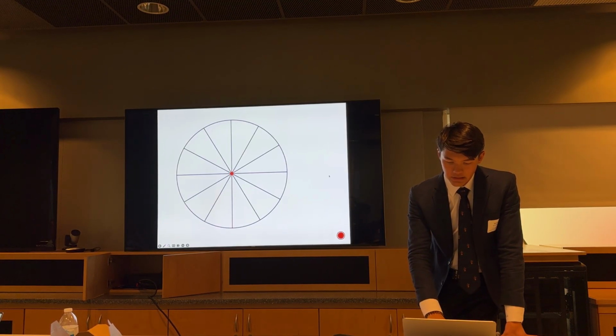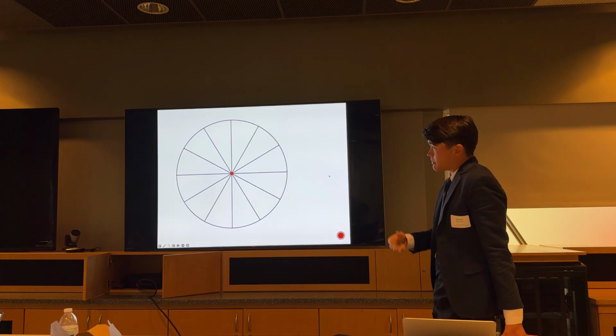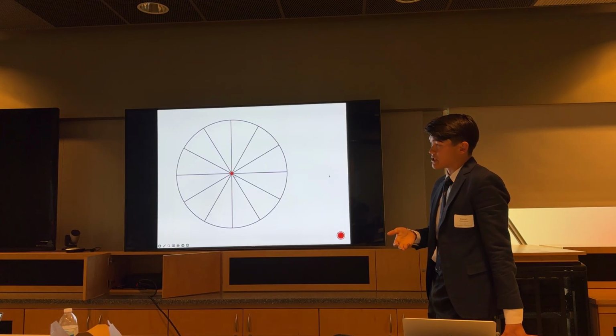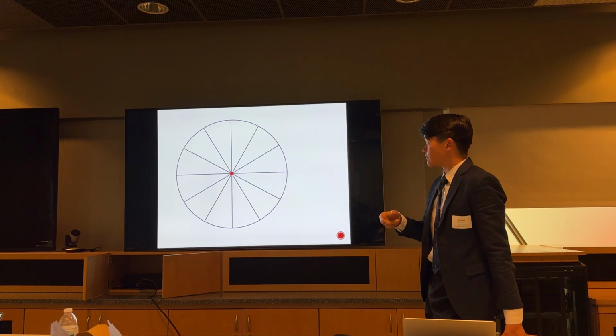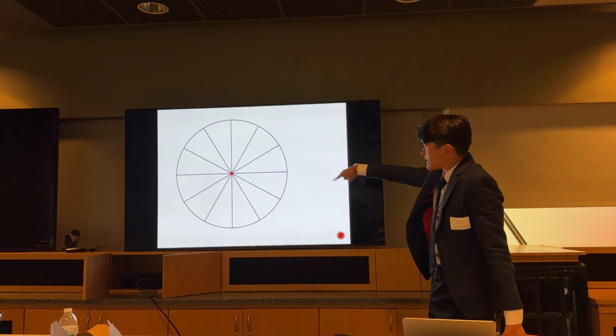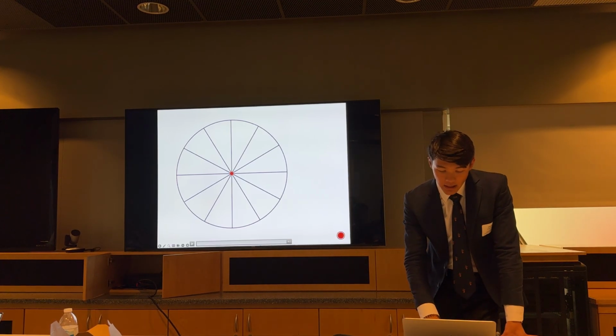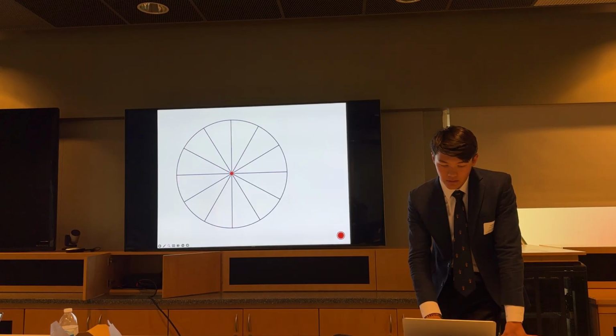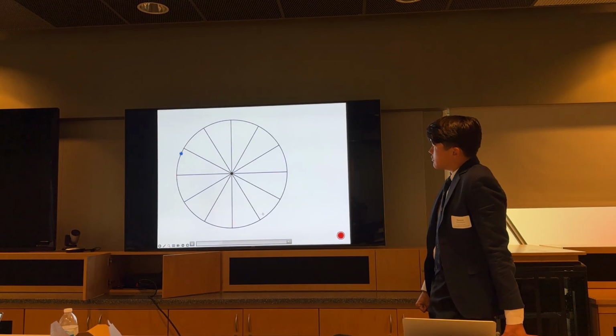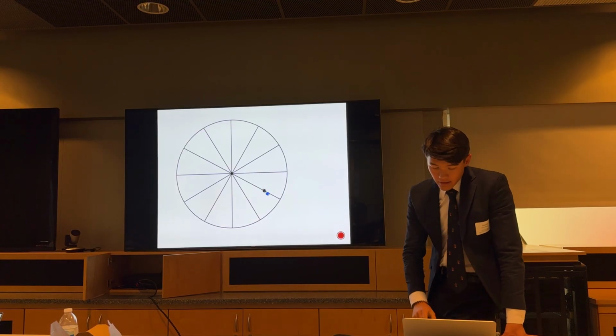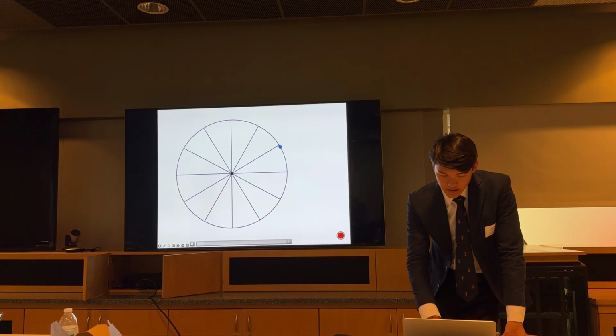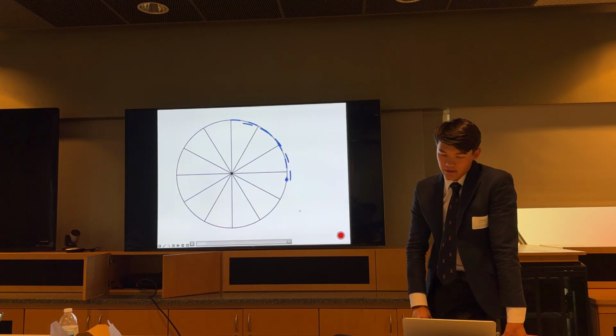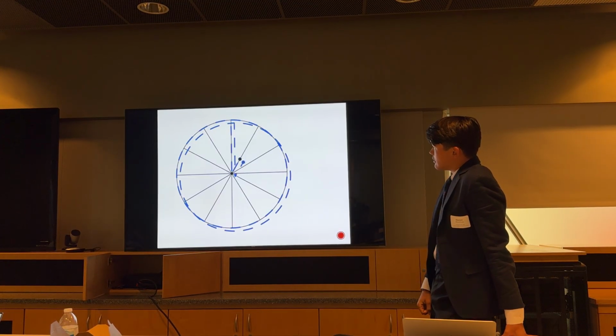However, there was likely noise introduced into the position signal of the electron beam because the position was actually encoded by just an analog voltage. So there was likely noise causing a digital jump like that. And when you add that to the position signal of the beam, you get a dot that moves around sideways like that. And if you then trace the path created by that beam with noise, you get exactly the pattern that we were observing.